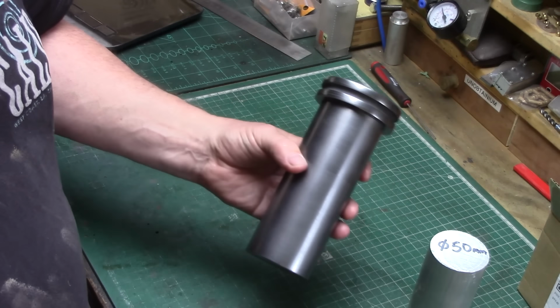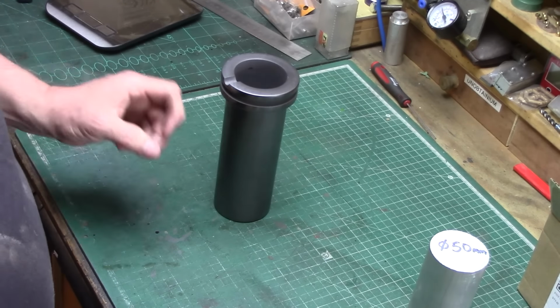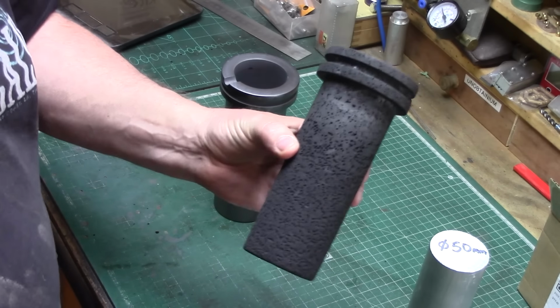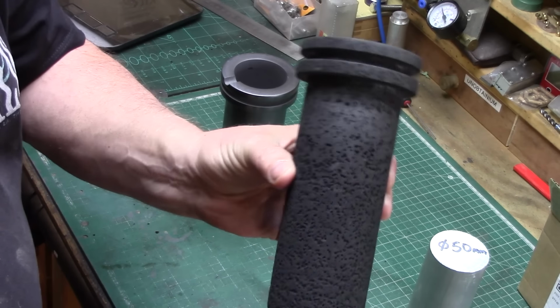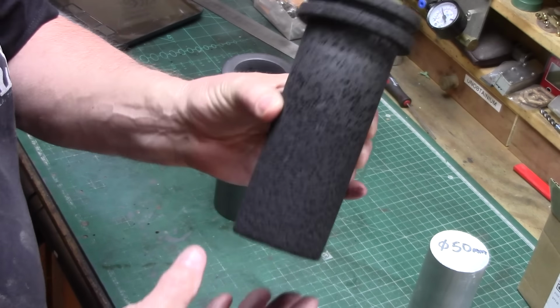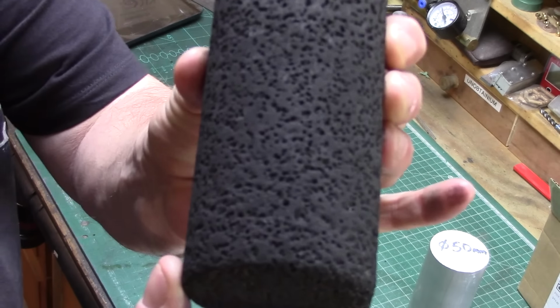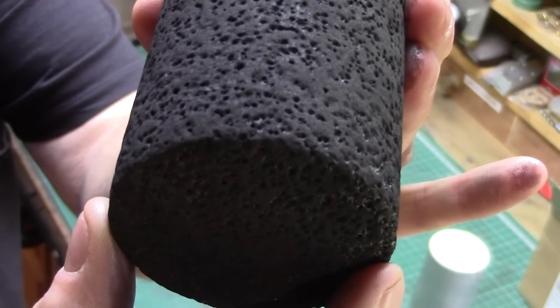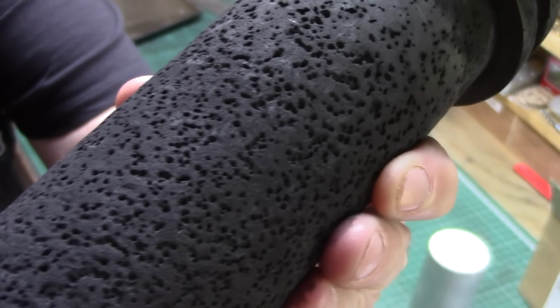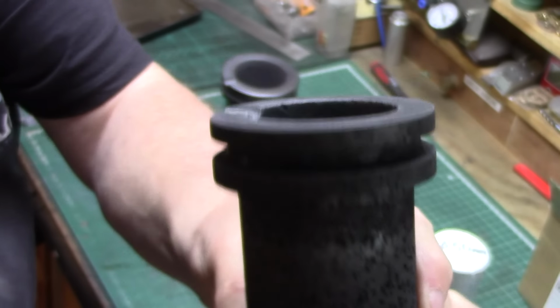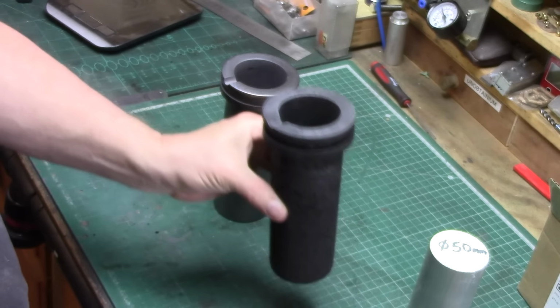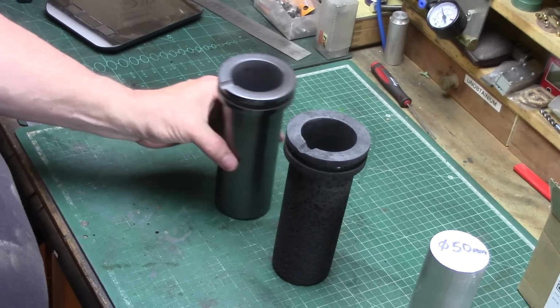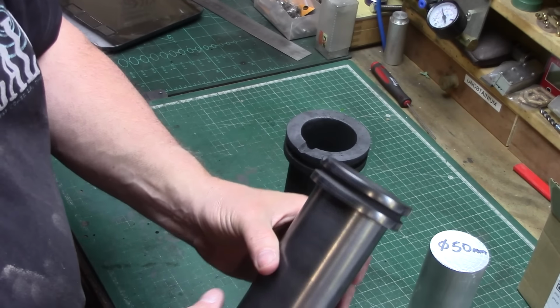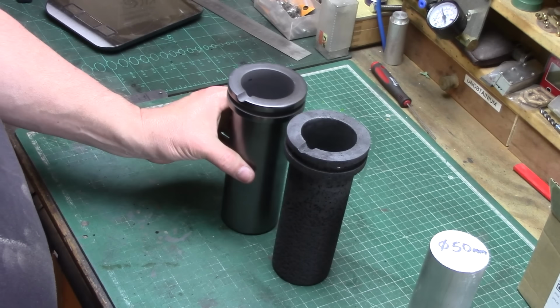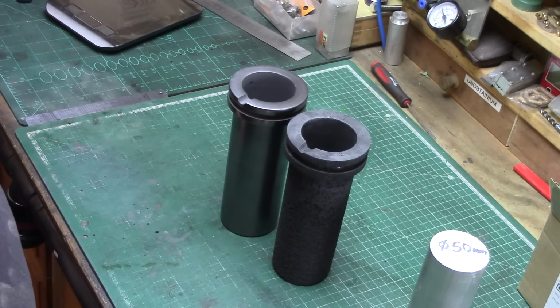Now this here is a brand new crucible which I have bought, and this is the one which came with the furnace after 18 aluminium melts, and as you can see it has become quite pitted as the graphite has degraded. So the new crucible was bought in readiness to replace this, as it is a consumable item. But I reckon it's still good for a couple more pours yet.